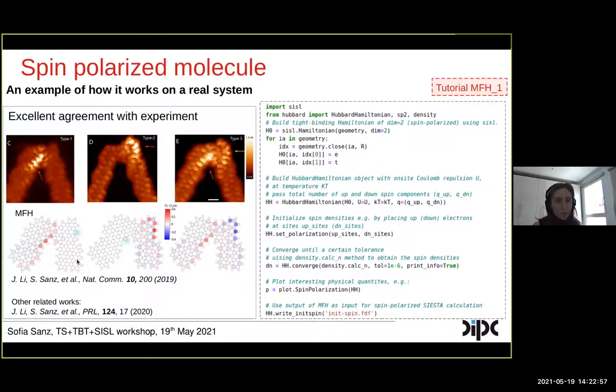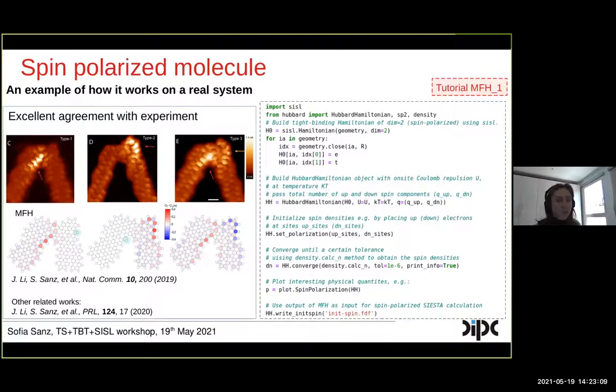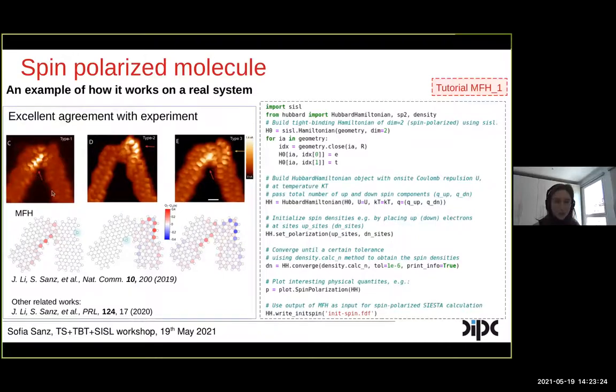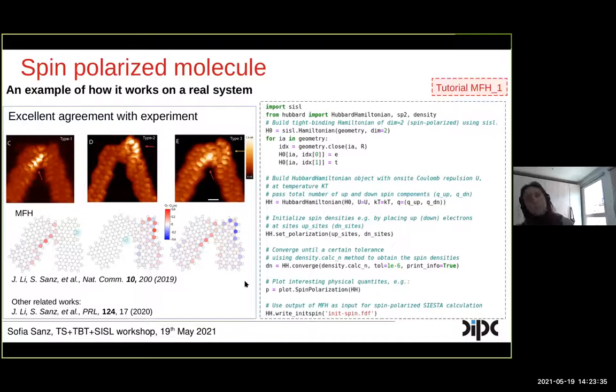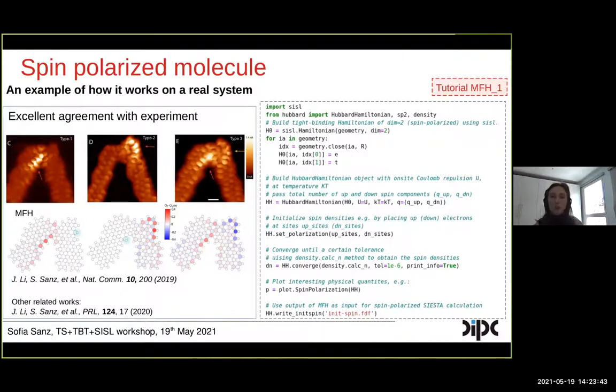Here I show an example of the spin polarization that we obtained using the Hubbard package for a particular molecule experimentally synthesized by the group of Nacho Pascual in Nanogune in Donostia, San Sebastián. I wanted to show the comparison between our theoretical predictions of where the spins localize in the molecule compared to the experimental images. The resemblance is very good between these two images.